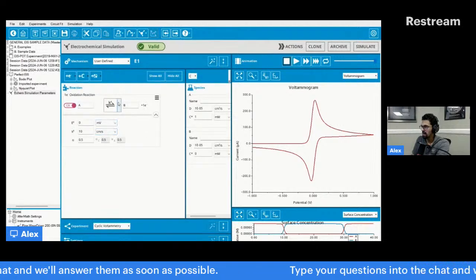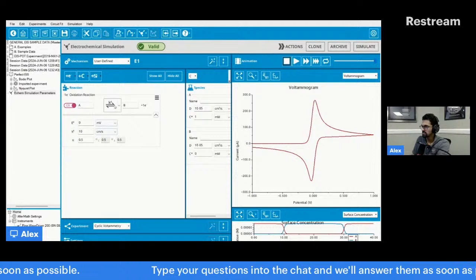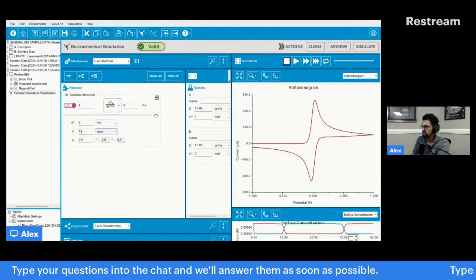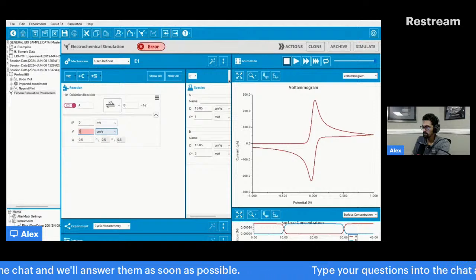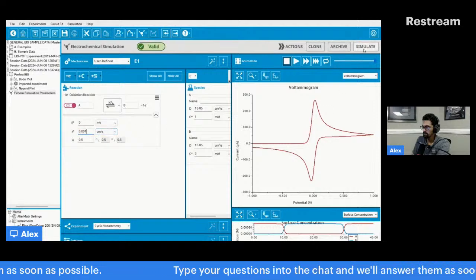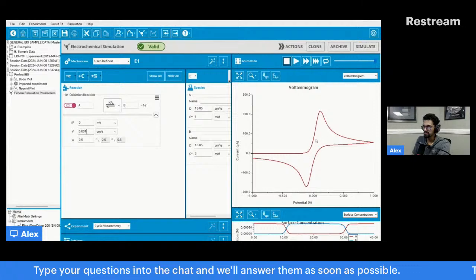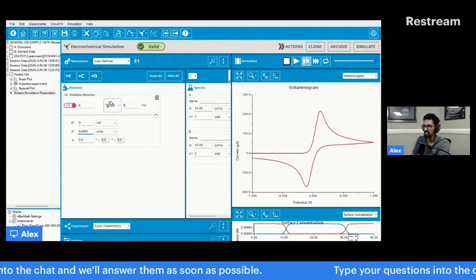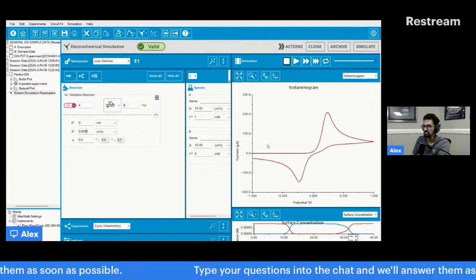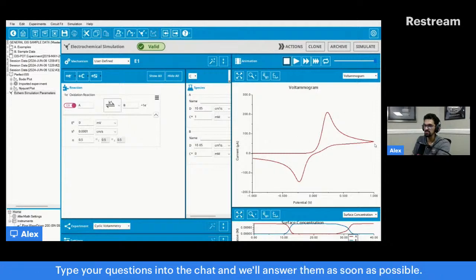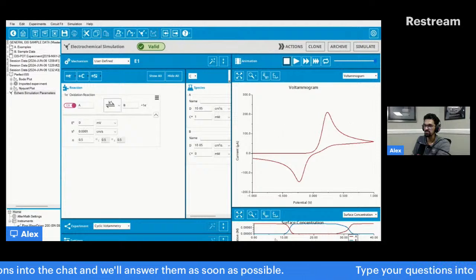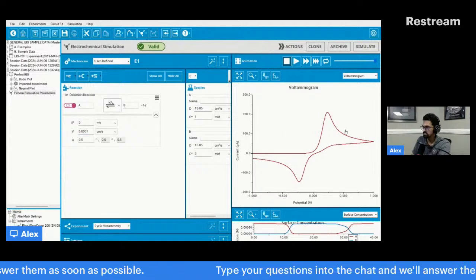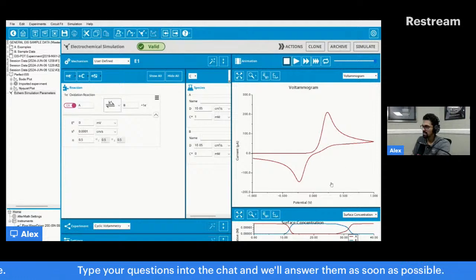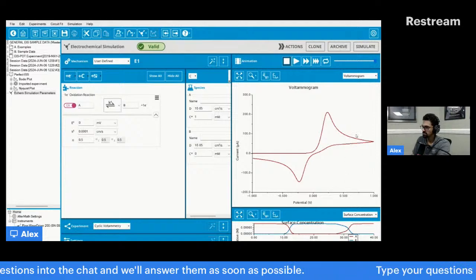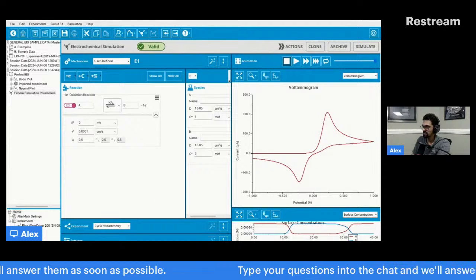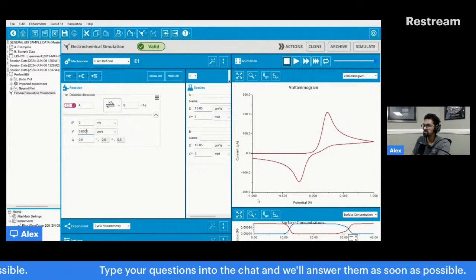Now, what if it's less reversible? What I can do is change the reversibility by changing this heterogeneous rate constant. If I change the heterogeneous rate constant, that's one way to create irreversibility. And what you would see is this peak separation, this peak splitting. And if I increase this by an extra order of magnitude, you'll see that as we become less and less reversible, this is the observation of how it changes. Okay. And then what happens to the graph if A is 10 times greater than that of B?